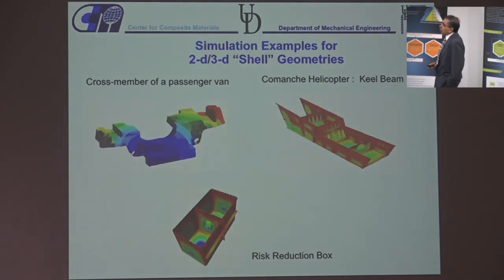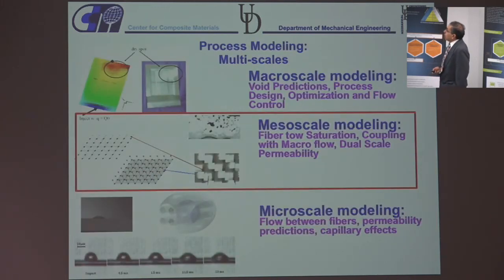And we can do very complex structures. One of the beauties of the simulation is that because of the way we do it, it's very fast. To simulate something like this with 10,000 nodes on a PC, it takes about 10 minutes. So it allows us to do optimization and look at different probabilities and so forth very quickly.